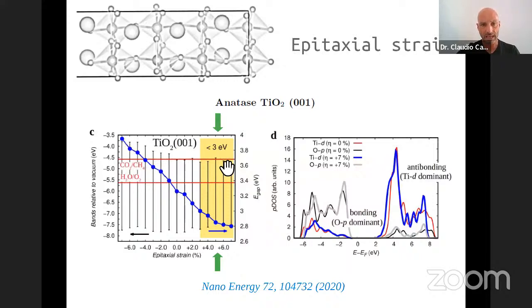However, how the band alignments change under the epitaxial strain was not too optimal for water splitting, right? Since on the side where the band gap is improved, the band alignments still are not good enough. So this point here should be a bit higher, and this point here should be a bit lower, closer to this line over here, right?